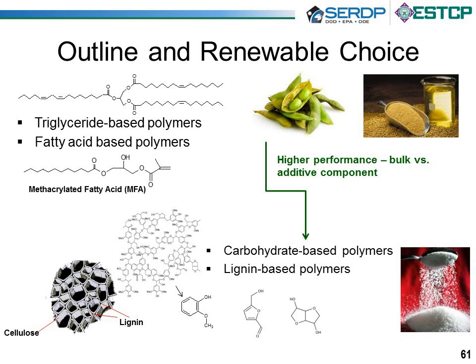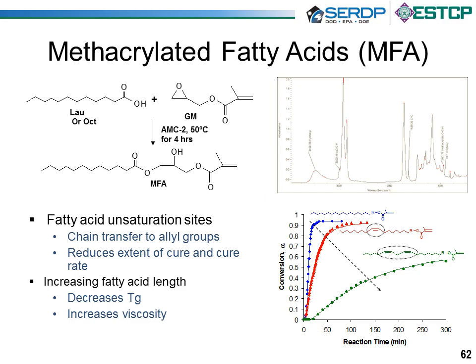So we invented these compounds called methacrylated fatty acids, or MFAs, which are a simple reaction of a fatty acid with glycidyl methacrylate, which is an industrial commodity chemical. And we produce this MFA. It's a single one-step reaction, no separation required. We made this in very high purity. And what we found is this is a good molecule. Because it has a methacrylate group on the end, it's capable of reacting and polymerizing with vinyl esters and styrene and other vinyl functional chemicals to make a cross-linked polymer.